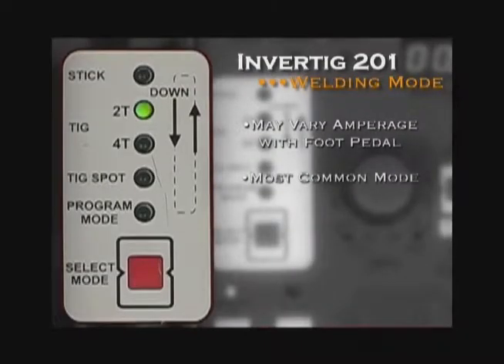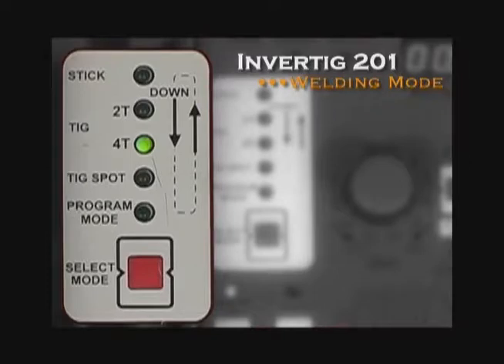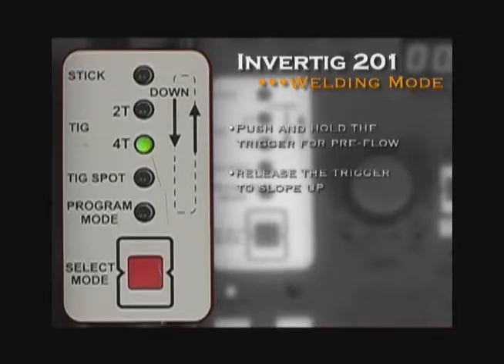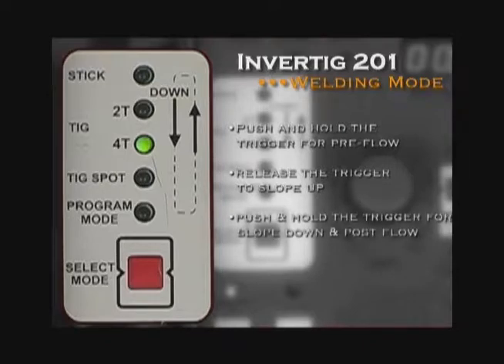The 4T mode is like a lock-on trigger on a drill and is used with the momentary contact switch. Push and hold the trigger for pre-flow. Release the trigger to slope up to welding current. Push and hold the trigger for slope down and post-flow. Release the trigger to stop. Do not use the 4T mode with the foot pedal.